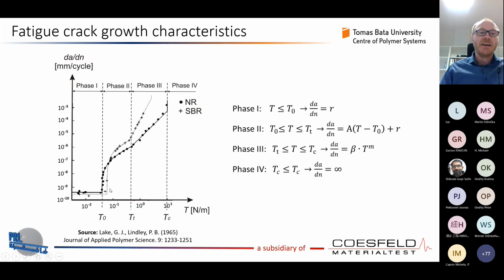Then we have phase 2. Phase 2 is defined with this equation, and this is a nonlinear characteristic within this diagram, coming to an interface with the next phase 3, which is well known as stable crack growth propagation, or Paris law, which is written here as well. We see exactly the power law for both materials. However, there is also one transient point labeled here.